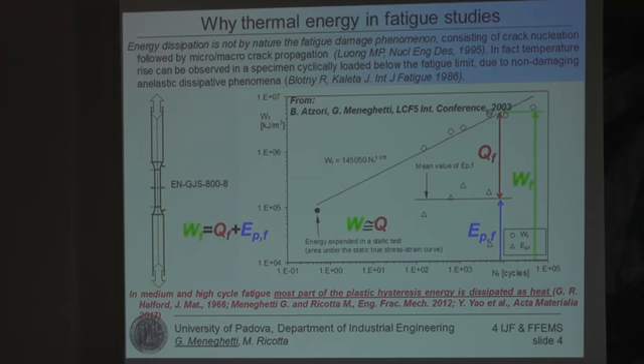Now, which is the problem? You see here that for a fatigue life of only 100,000 cycles, the total energy to fracture the specimen is about 10 to 7 kilojoule per cubic meter. Most of such an energy is dissipated as heat, and the stored energy is about 2 orders of magnitude lower than the total mechanical energy expended during the fatigue test.